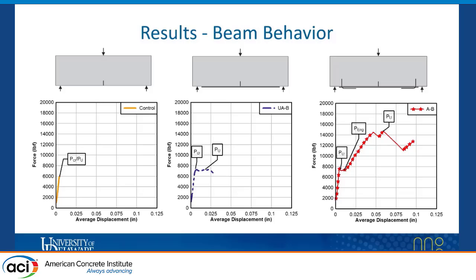All right, now moving on to the beam results. So the control unstrengthened beams demonstrated linear elastic behavior up until concrete cracking, and then the specimens failed. When CFRP was applied to the unanchored strengthened beams, again, linear elastic behavior was demonstrated up until concrete cracking. However, following concrete cracking, you see a plateau region here, which is the demonstration of the progression of debonding up until ultimate capacity, and then the specimens failed.